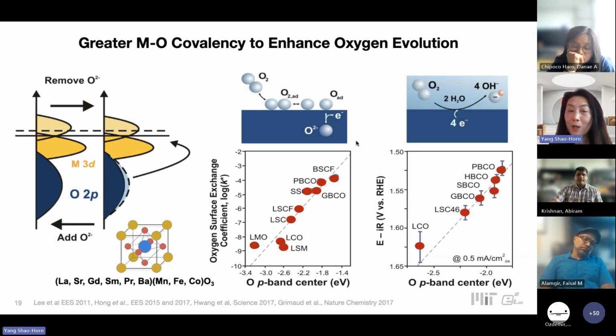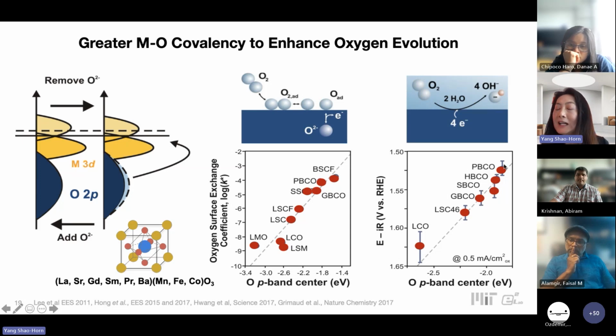Right. So through this correlation, one may say that the oxygen p band center alone is a major descriptor that can tune the rate of such reactions. And similarly, such a descriptor can also increase the rate of oxygen evolution in basic solution, from hydroxide ions to molecular oxygen, for the series of cobalt perovskites from lanthanum cobaltite all the way to A-site 2+ substituted A-site double perovskites. Considering a Tafel slope of 60 millivolts, we're looking at roughly 2 or 3 orders of magnitude of increase for the OER catalytic activity. So this essentially is a very simple empirical correlation.